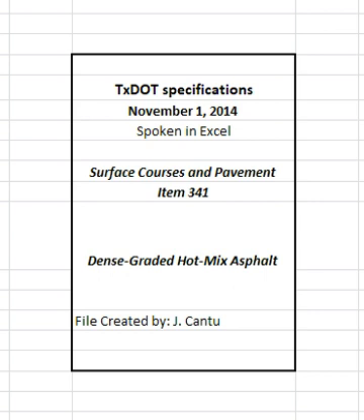Compact the pavement uniformly to contain between 3.8% and 8.5% in-place air voids. Take immediate corrective action to bring the operation within 3.8% and 8.5% when the in-place air voids exceed the range of these tolerances. The engineer will allow paving to resume when the proposed corrective action is likely to yield between 3.8% and 8.5% in-place air voids. Obtain cores in areas placed under exempt production, as directed, at locations determined by the engineer. The engineer may test these cores and suspend operations or require removal and replacement if the in-place air voids are less than 2.7% or more than 9.9%.